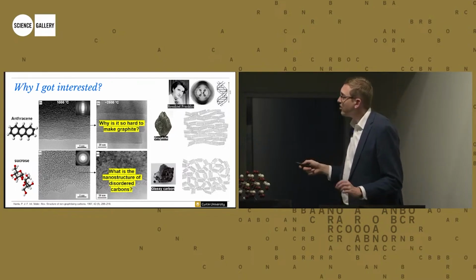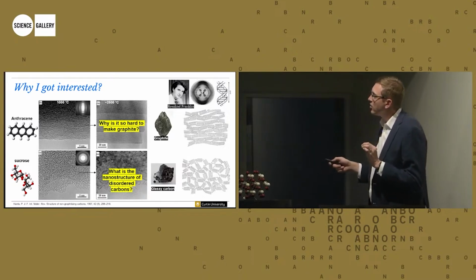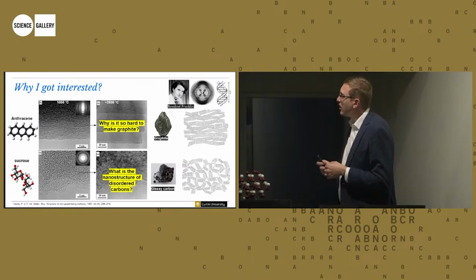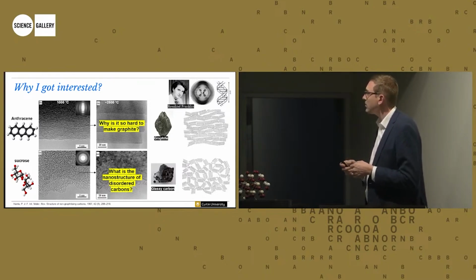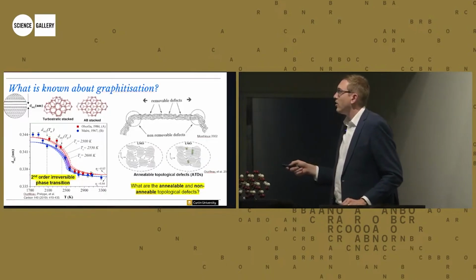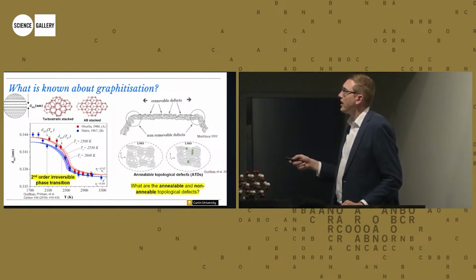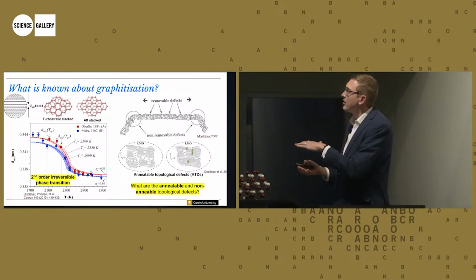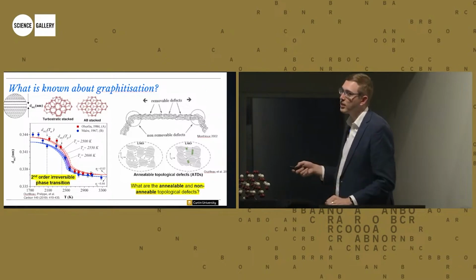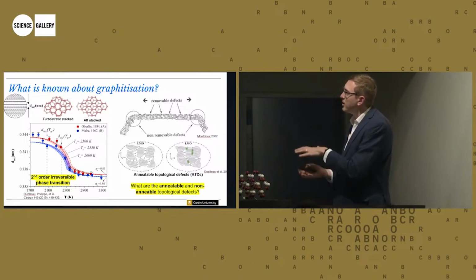But before she did DNA, her first passion was carbon, and she looked at X-ray diffraction and suggested that there are small bits of graphite that are misaligned inside of disordered carbon, but aligned in graphite. And there's been a lot of work done on these defects. The defects actually stop the layers from coming together. They hold them apart, and that's a problem because to get the lithium in there, you need to separate the layers. So the defects hold the layers at a very set distance and mean that the lithium cannot get in. That's why you have to heat to high temperatures. The layers come close together and then they're all free to move up and down.